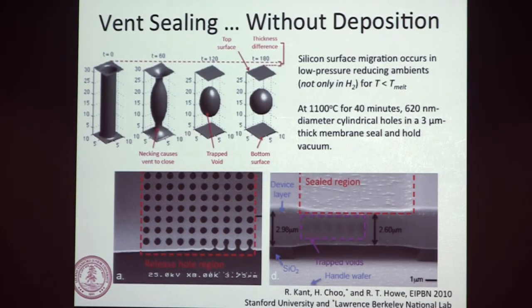So lastly, I'm going to show work that is EIPBN in 2010. Hyuk Choo is a Berkeley guy who became a postdoc at Lawrence Berkeley Lab. He just moved to Caltech as a faculty member. Rishi Kant is my PhD student, and he worked with Hyuk on this, seeing if he could extend the silicon migration phenomenon that people call hydrogen annealing. Those that are into silicon technology would know that you have extreme mobility of surface atoms on silicon, well below the melting point. Melting point's 1412. At 1100, you see things like these holes flow and seal. Okay, you're not melting it. It's a surface migration phenomenon.